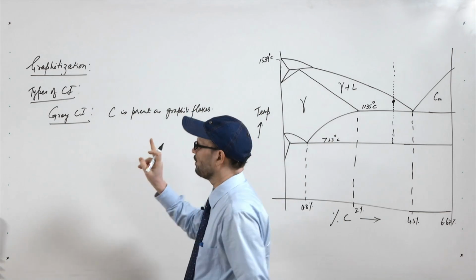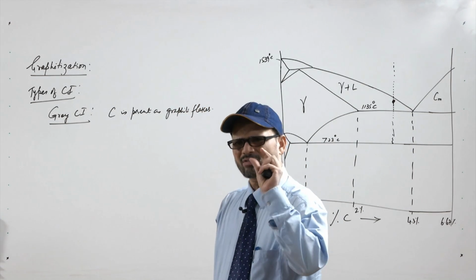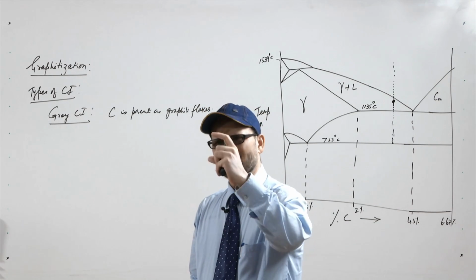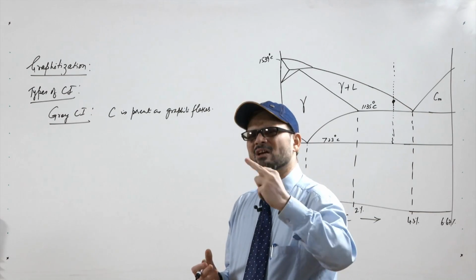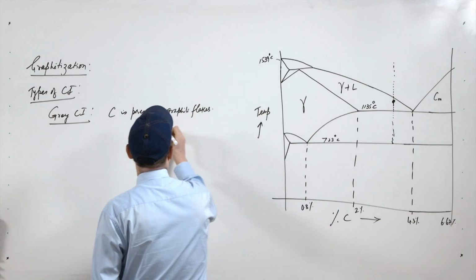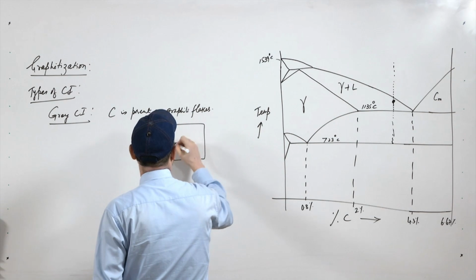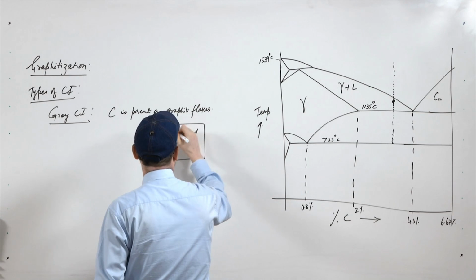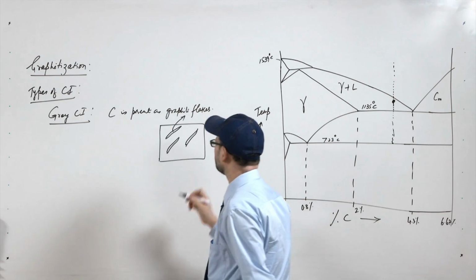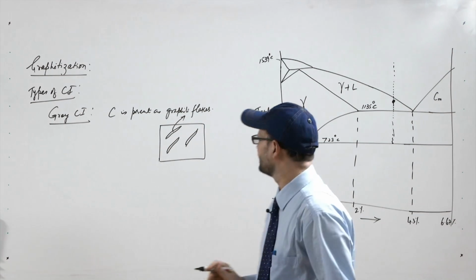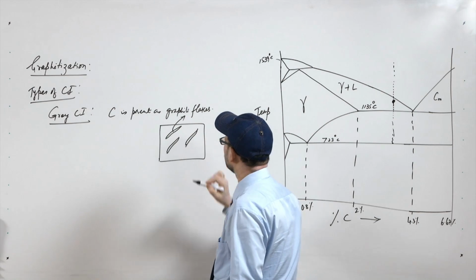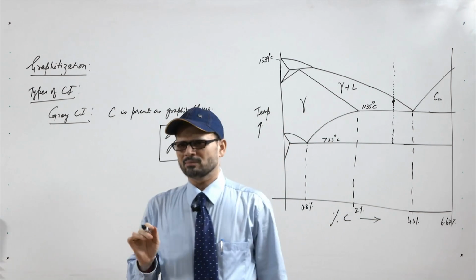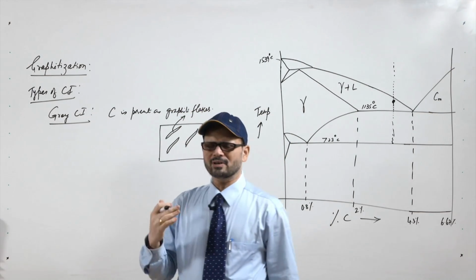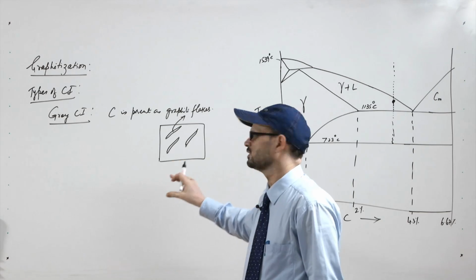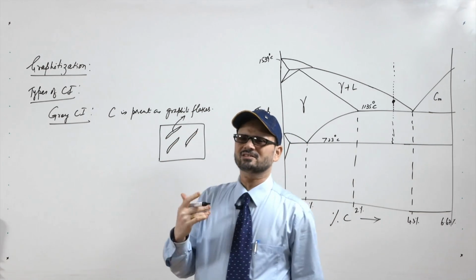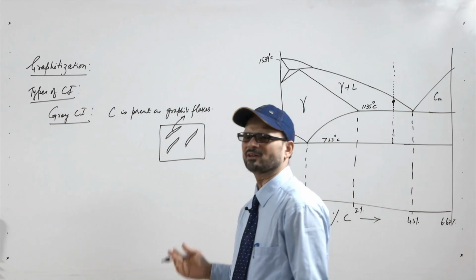Now, in the grey cast iron, the value of carbon as well as silicon has to be on the higher side, and also the cooling rate has to be moderate. In that case the grey cast iron is formed, and in the grey cast iron your flakes are like this. So, these are the graphite flakes which have pointed ends, and this gives the material some inferior properties when subjected to tension. But grey cast iron has other very good properties, like good machinability and good damping capacity. That is why grey cast iron is very much favored for typical applications like machine beds, and many components are made by grey cast iron.